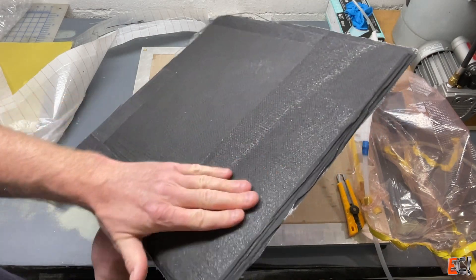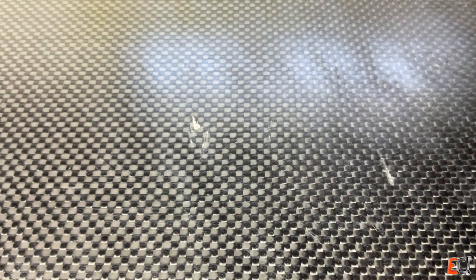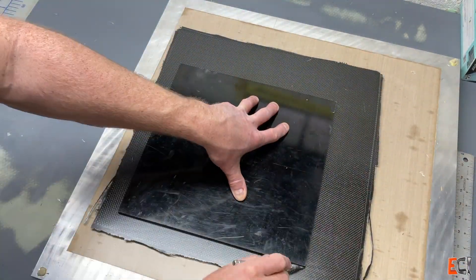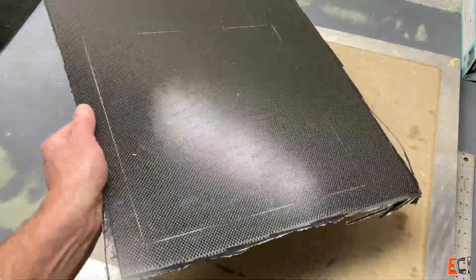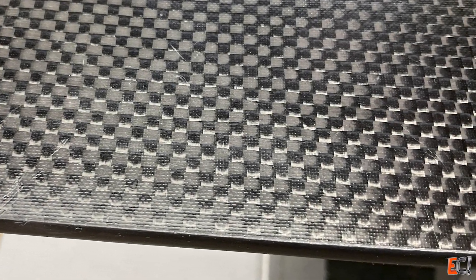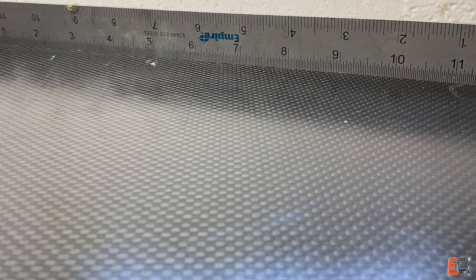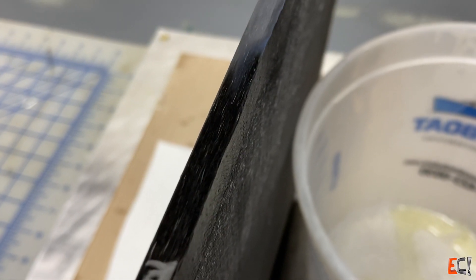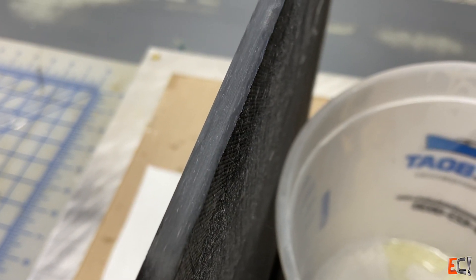You can see a little bit of spray glue. There's the defect from the Teflon and another. The Teflon is great, but it's definitely not something that's going to give you a perfect surface. It's totally repairable. You can cut things out and patch them together. Here I'm cutting out the square with my one-foot template using a carbide scribe. It's a really nice way to mark material that won't get wiped away with solvent or wear off. Here's the trimmed up piece. You can see that nice surface. It came out very uniform and flat, no warping. Here I tried to put some acetone to show just how random those fibers are. It does not show layers like you would typically see with a stack of material.